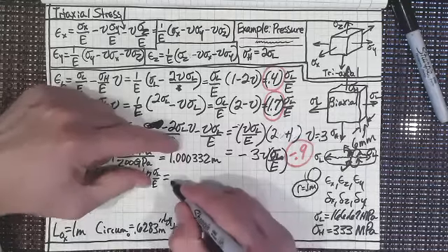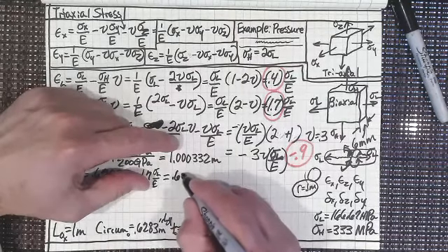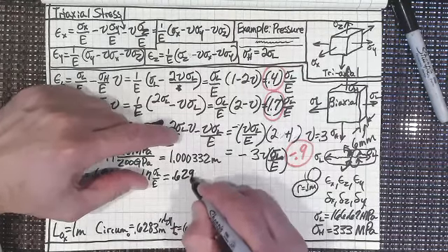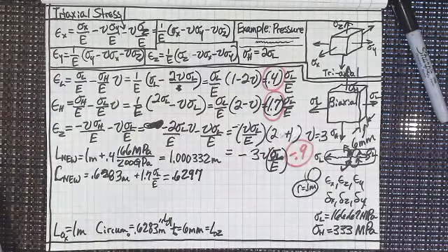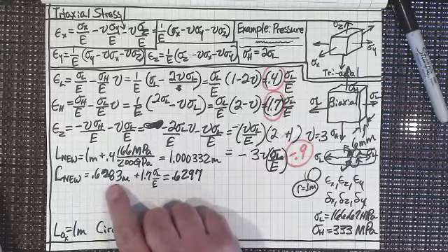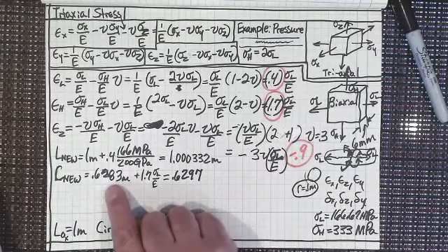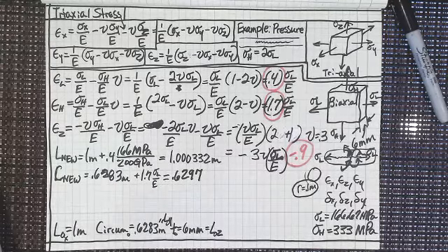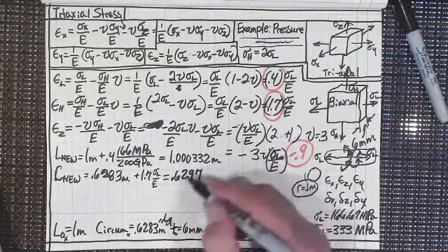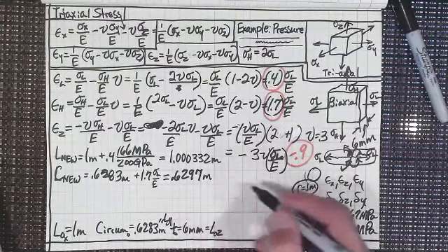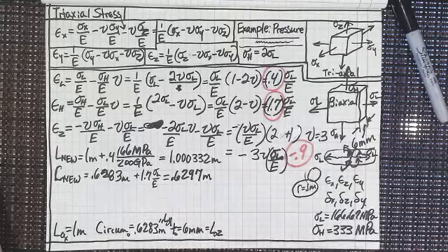So altogether, I get 0.6297. So you can see that there is a little bit of addition there. In fact, it would be 0.0014, so 0.6297 meters. The circumference has expanded. The length of the scuba tank has gotten just a dash bigger. You can't even notice it.